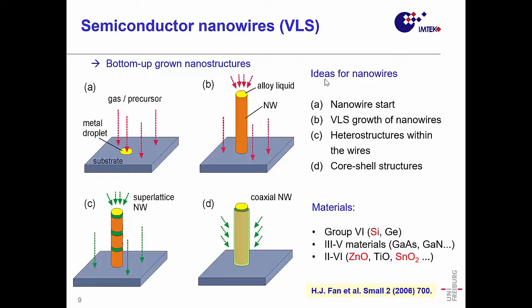It's like a kid's experiment, taking a glass of water with a lot of salt, and you put something in, and then salt crystals are growing. In a way, it's the same as what we are doing here for this nanowire growth. You can play with the gases to have superlattices. If you play with the temperature, you're changing the growth drastically, and that means you might end up with, instead of a VLS growth, a VS growth. That means the dot gets solid again, and you get maybe a shell, as you see in image D. So I will show you some examples from that.